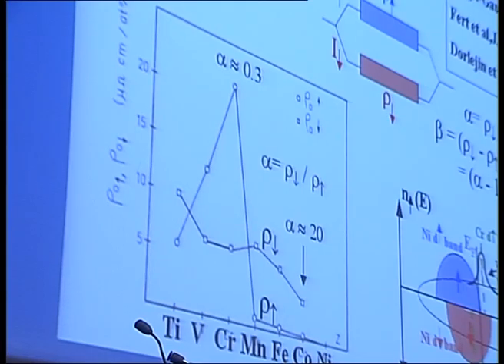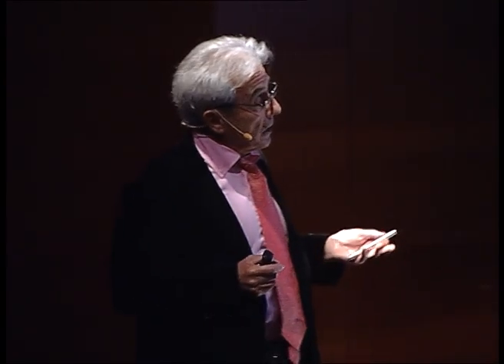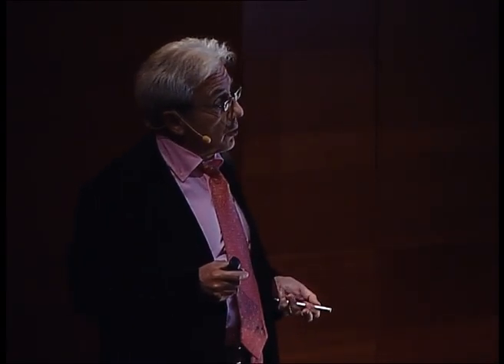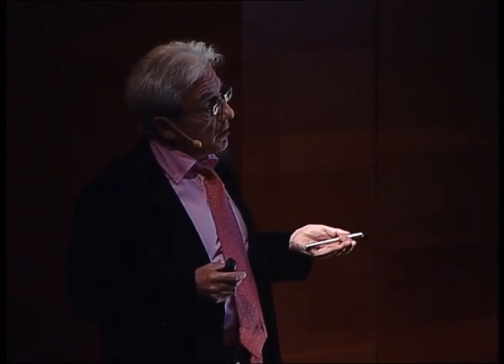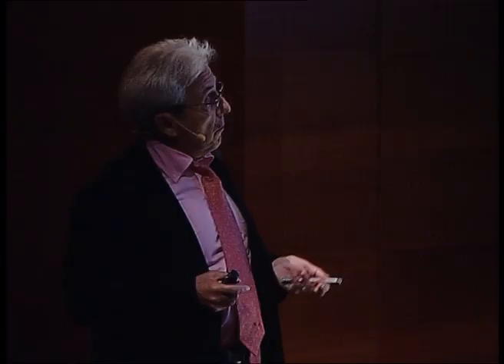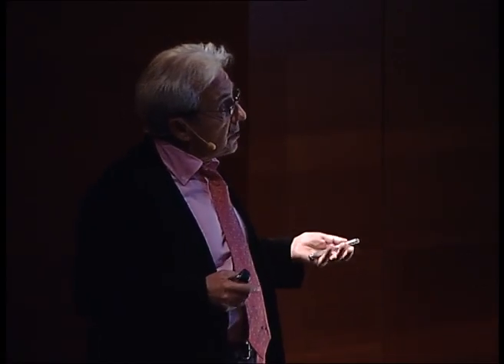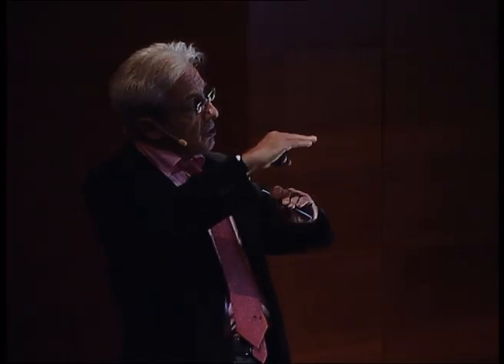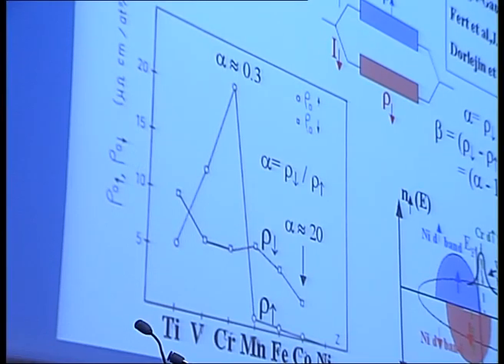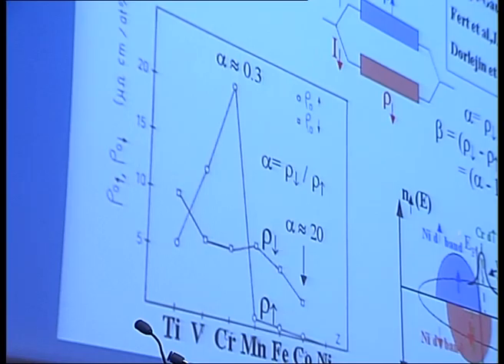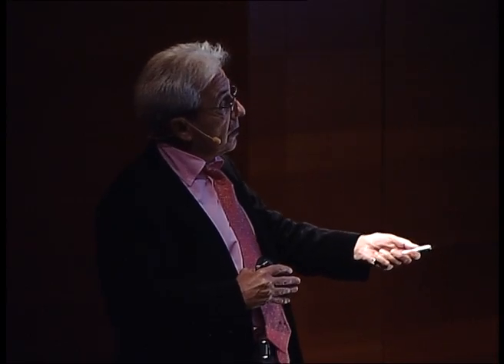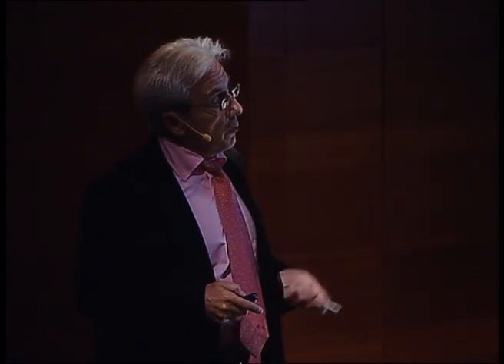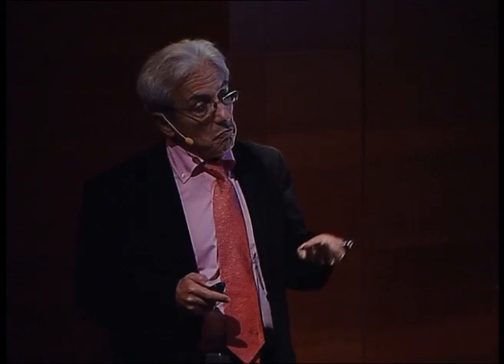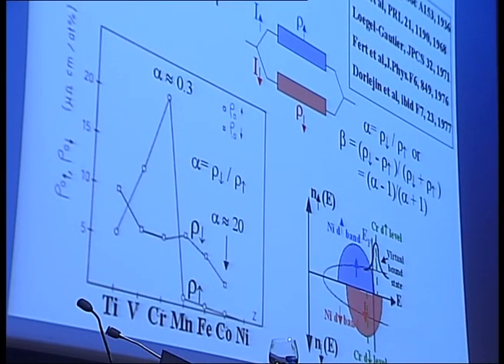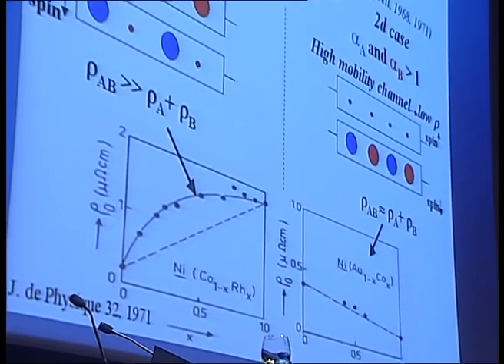So these results are not new. They are from my PhD thesis in '70, a long time ago. And at this time, they could be understood by using the electronic structure model, for example, developed by Friedel. If one wants to understand these results, one considers that the resistivity is controlled by the relative position of the impurity level and energy band for each spin direction. And this relative position is different for spin up and spin down, and explains more or less this curve. Also, at this time, we had some practically some concept very close to the concept of the giant magnetoresistance in experiments in ternary alloys.